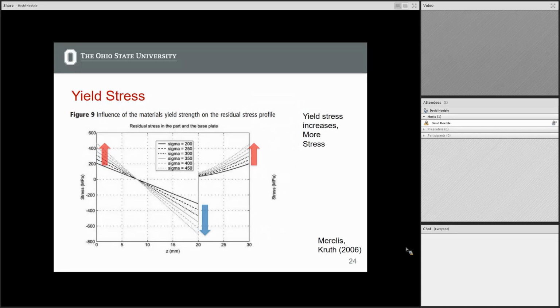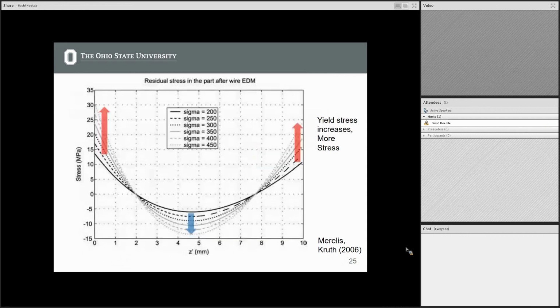So then lastly, this is just taking a look at if we vary some of the material properties that we're actually printing with. So this is varying the yield stress of the material, and how it's going to affect your build. So you can see we get an increase in both the tensile and compressive stresses in the part, as well as the base plate. And we can also see that those trends hold for the stresses that are going to be in the part after removal.